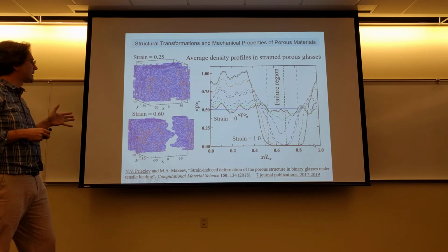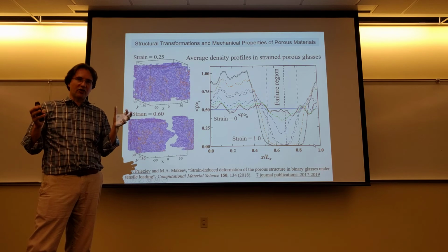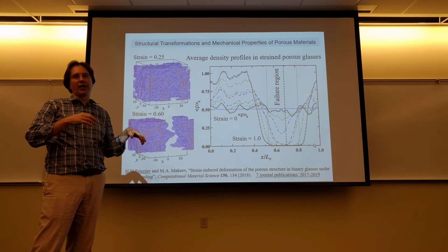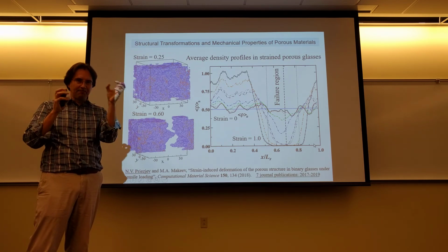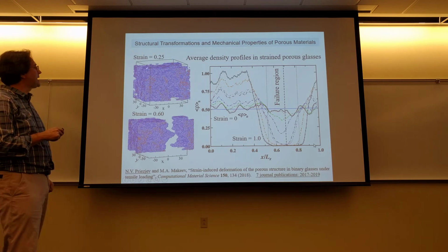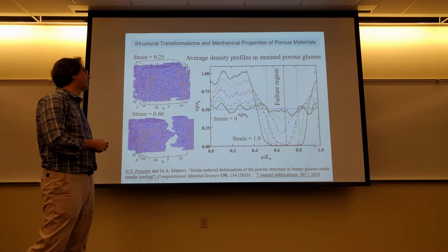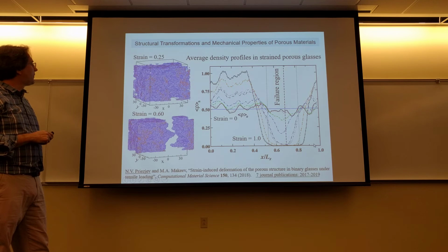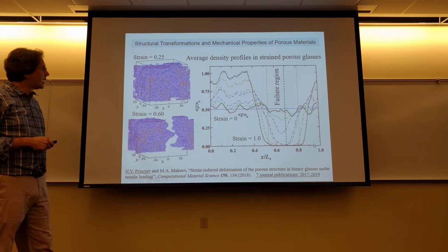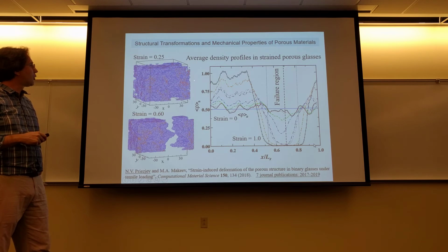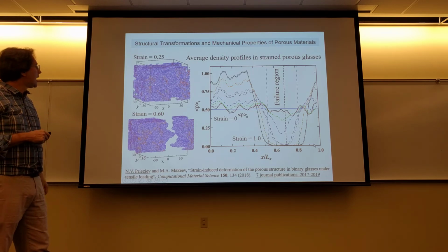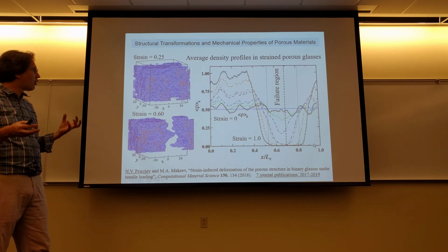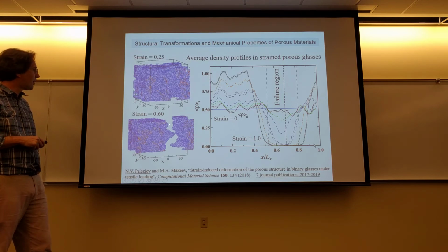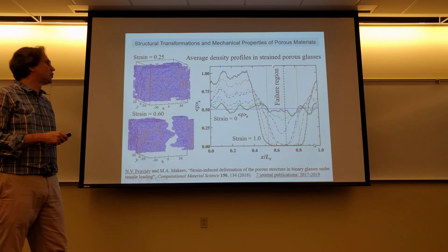giving rise to porous structures like this. Depending on the average glass density, this structure might have porous networks that are percolating, or on the other limiting side of large densities it would be a mostly solid phase with porous inclusions. What we see here is some kind of intermediate case with medium-range porosity. When you deform a material like this, one can trace the pore size distribution and the average glass density. Our main conclusion is that regardless of the deformation protocol, in this case simple tensile loading, small pores in certain regions coalesce with each other, but in some other regions will form a dominant pore that will ultimately lead to failure of the material.